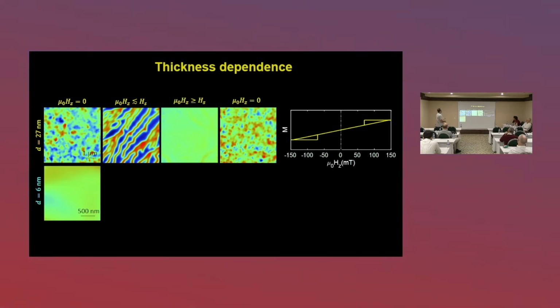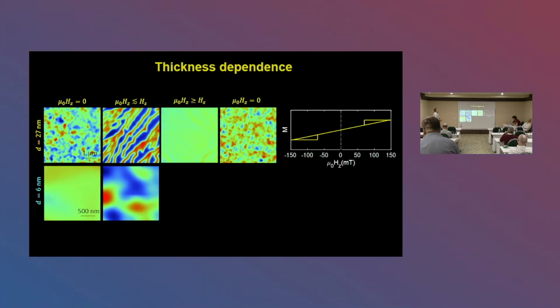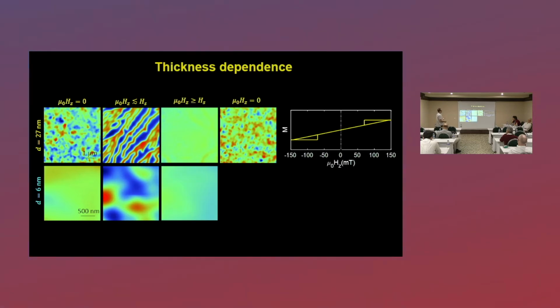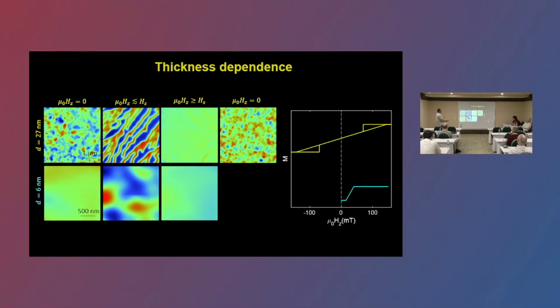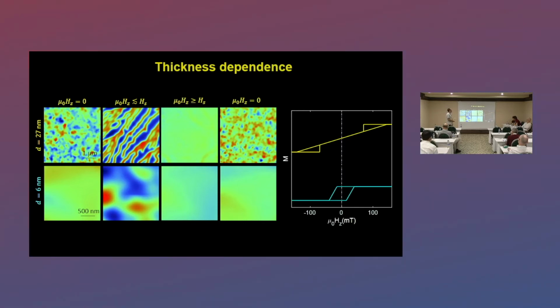However, if we are below a certain thickness, around 10 nanometers or so, the sample stays magnetized at 0 field. It does go through a coercive field, as you would expect from a standard magnet. It does saturate, and if you go back to 0, it stays magnetized. It reverses its magnetization, and if you go back to 0, it stays magnetized. So for thin films, it behaves like a hard magnet, and for a thicker film, it behaves like this bow tie. Okay, so I complete the picture here.